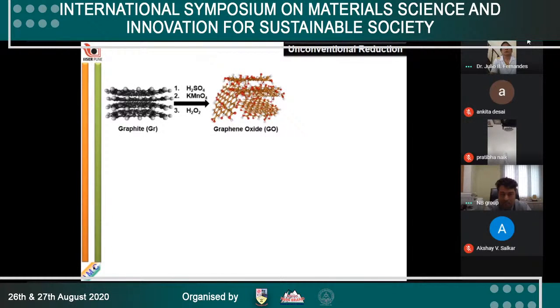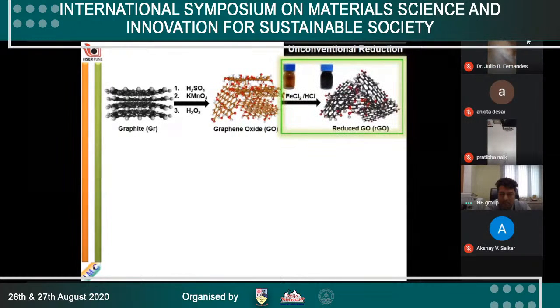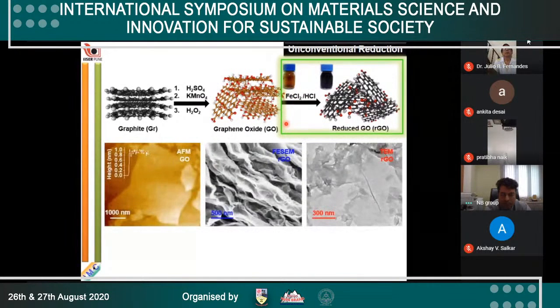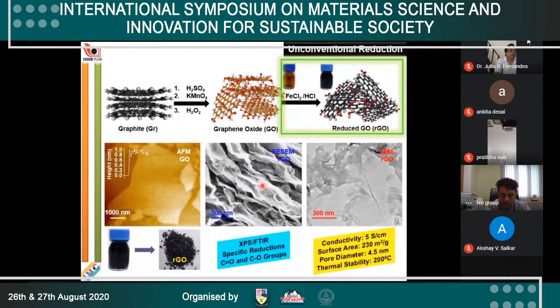Instead of the crowded path of using hydrazine, we walked through a new path and brought the chemistry of transition metal salt into the picture. To start with, we have explored iron 3 chloride. Here are some microscopic images of graphene oxide and reduced graphene oxide. You can clearly see that very thin layers of GO and RGO are being produced. This reduction is specifically influencing the basal plane of graphene oxide. So the reduction is happening typically in the basal plane and not preferably on the edges.